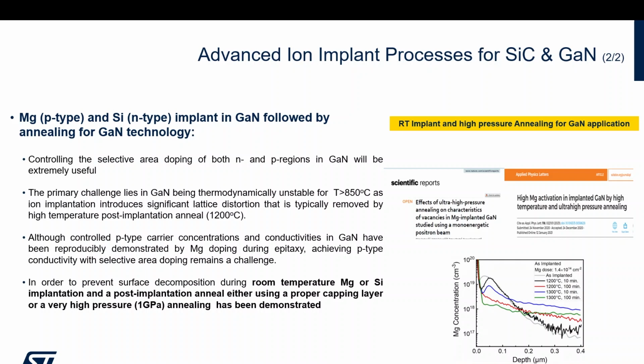Probably one thing that, again, before the conclusion, for my kind of experience in the past, I used to be, more than 20 years ago, an ion implanter guy. So I like wherever possible to use ion implantation for doping. In silicon carbide, in gallium nitride, it is difficult because of the problem of the activation. But there is a revamp of work about the possibility of using capping layers or even high pressure during annealing, which is coming back. And I see papers, especially from Japan, which are coming up in order to understand if it's possible from a manufacturing point of view to use ion implantation. My opinion is that we are going to explore this very much, because it gives you a freedom that, in my opinion, you cannot get by only epitaxy.